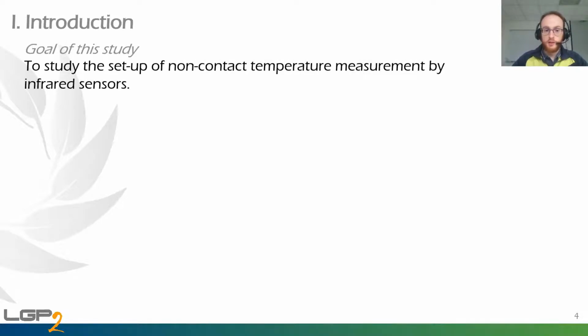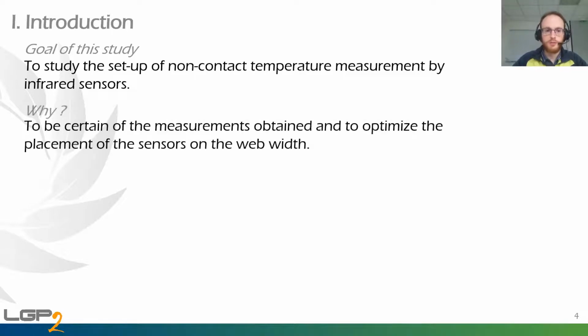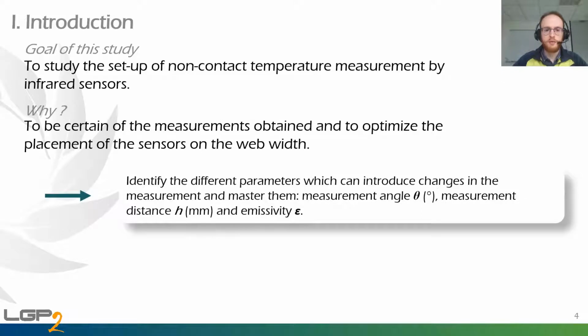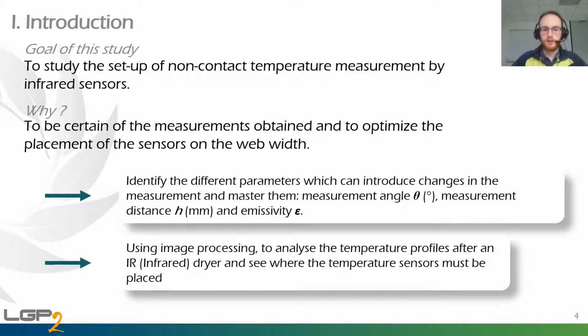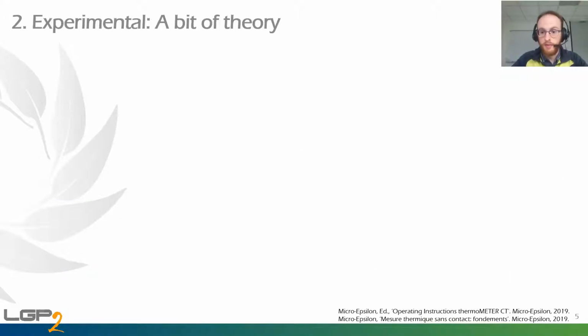In order to set up a non-contact temperature measurement by infrared sensors. Why, you will ask? It's to be certain of the measurements obtained and to optimize the placement of the sensors on the web width. So first of all, we're going to identify the different parameters which can introduce changes in the measurement and master them. We have the measurement angle theta, the measurement distance h, and emissivity epsilon. Then, using image processing, we will analyze the temperature profiles after an infrared dryer and see where the temperature sensor may be placed.